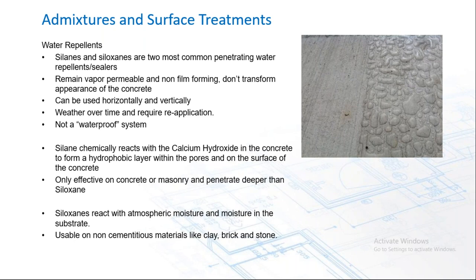They do weather over time and do require reapplications as they do weather away. And once again, not a true waterproof system in the strict sense of the word. Silanes chemically react with calcium hydroxide in the concrete to form a hydrophobic layer within the pores and on the surface of the concrete. Really only effective on concrete or masonry, and penetrates much, much deeper than the siloxane. It does require that calcium hydroxide to react with.